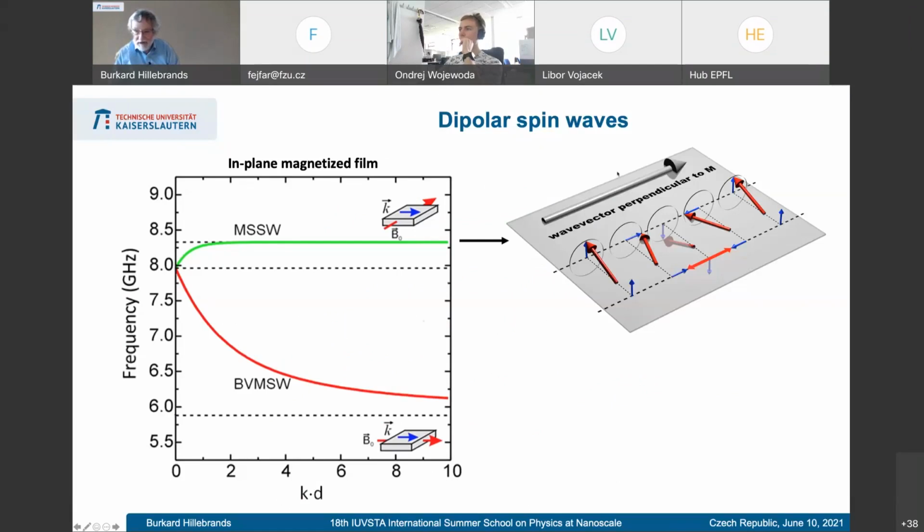If this is the wave vector of the propagation, the magnetization is perpendicular, so the moments lie in this direction, and they precess. Just take this particular graph and plot the dynamic part of the magnetization, shown here by the blue arrows, like little magnets. You see a particular case where these magnets are oriented head to head.